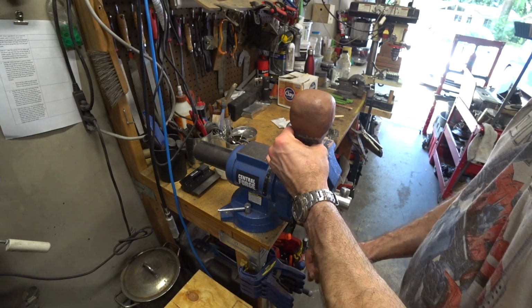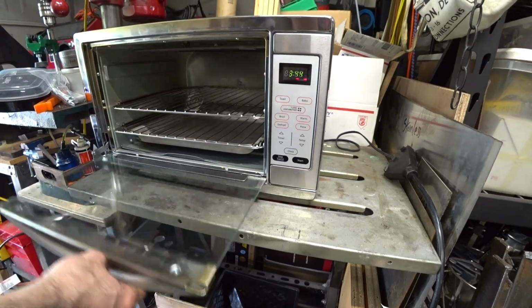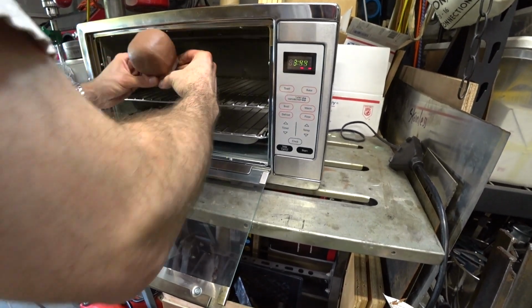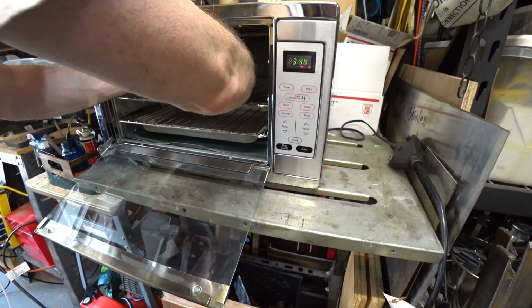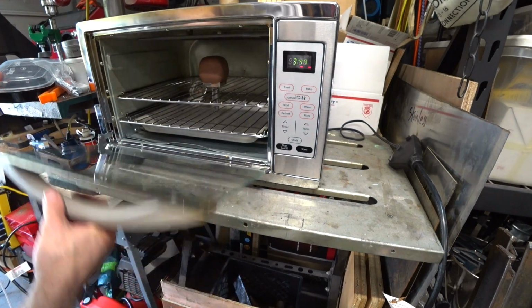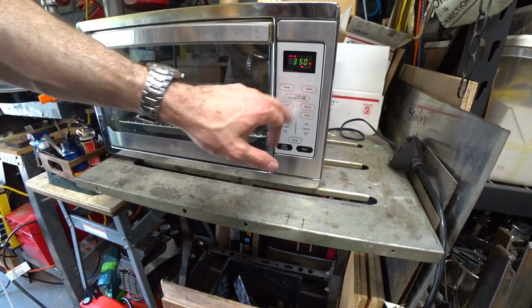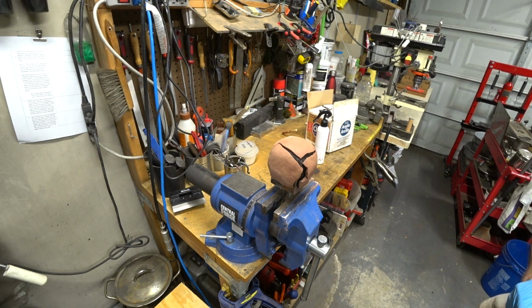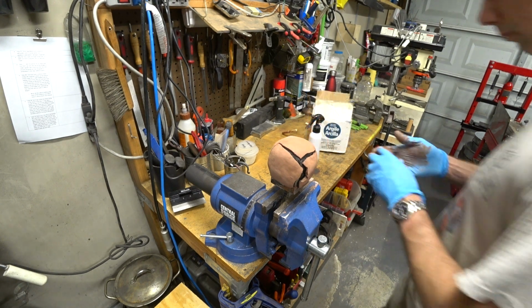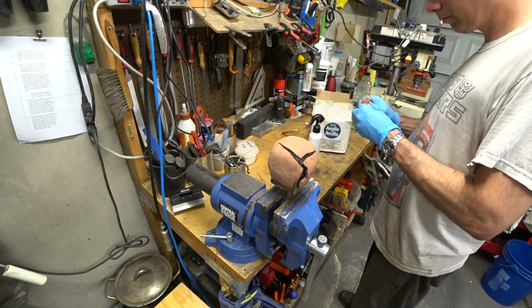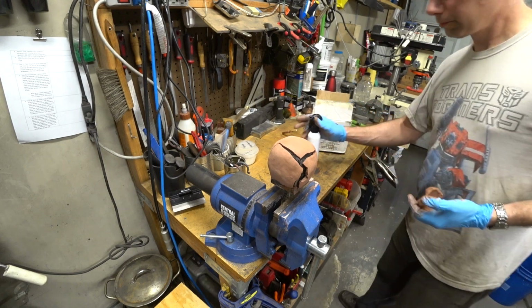Once it's all done, you want to let it dry for a while, and then you can put it in an oven at low heat to dry off any remaining moisture. It's actually much better to let it dry completely without using the oven. You're going to get less cracking that way, but I was just in too much of a hurry. So you can see I got a lot of bad cracking, so I'm going to patch that up with some extra clay and then allow that to dry.